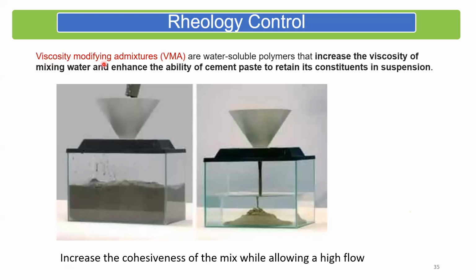And that's where we started developing these viscosity modifying admixtures. What these do is increase the viscosity of the mixing water. And basically what it allows me to do is to retain all the constituents in suspension, not allow the liquid part to separate out under pressure. It increases, like you see here, the cohesiveness of the mix while allowing a high flow. So you have this concrete which is being poured into water, and you can see that the lighter ingredients start separating out, and the heavier ingredients settle at the bottom. And that's what would happen if you just typically dump concrete in water. But if I mix in VMA, because VMA has this ability to hold all the ingredients together, I can pour concrete and it basically keeps all the ingredients together.